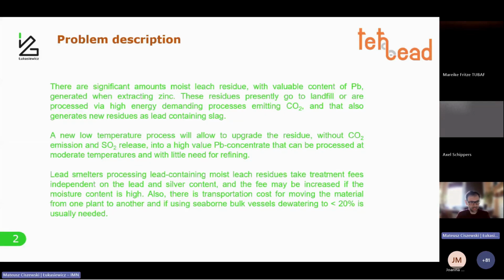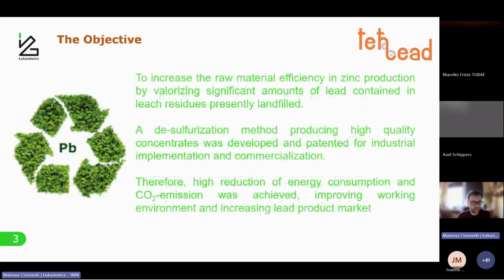Generally, a significant amount of leaching residue is produced that contains a significant amount of lead. These leaching residues, in our case from the zinc industry, are either disposed of or landfilled in some cases, or they can also be processed by lead smelters, but that involves additional fees for the transportation of quite heavy, moisture-containing materials. So the objective was to develop a technology that can face this problem and recover this lead.